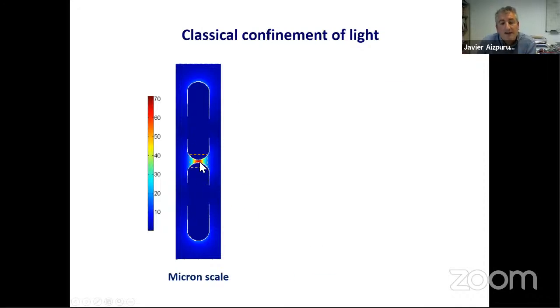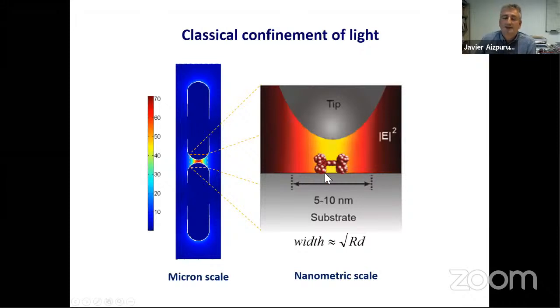And if you zoom in here, you can still do this same classical description at the nanoscale level, and one would see that you get this trapping of plasmonic light on the order of 5 to 10 nanometers. And this 5 to 10 nanometers is pretty much the lateral extension of a plasmon in a cavity like that, which will depend on the tip radius and things like that. So you can do that classically, but when you start paying attention to what kind of features